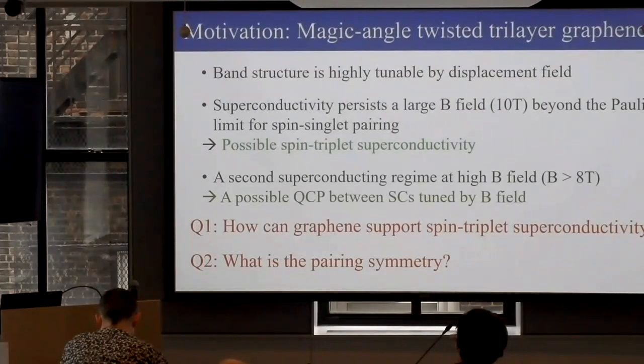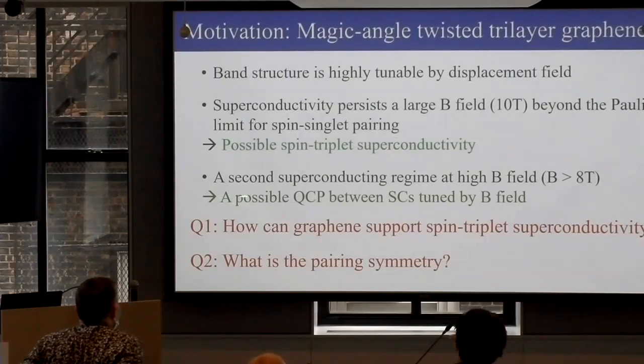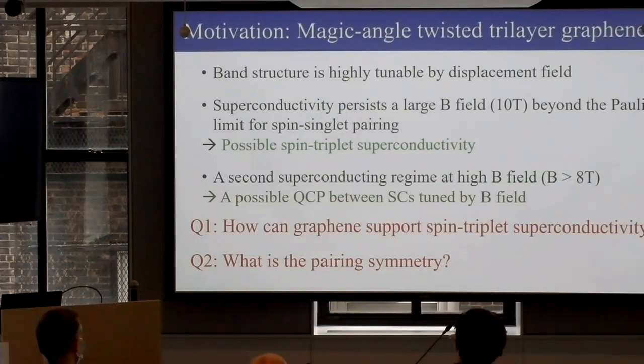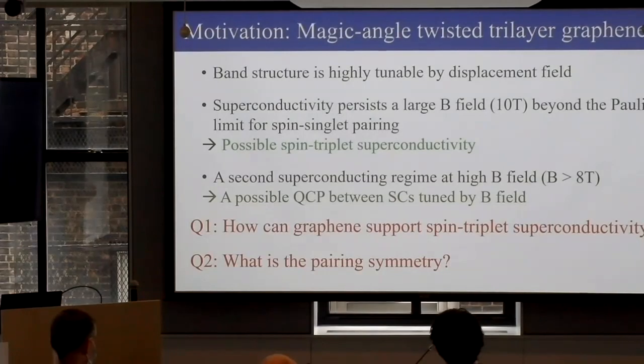Now the last topic which I want to talk about, because this is the electron, I said phonons are not. These two groups, Santa Barbara, Columbia, and MIT compete. So Pablo came up with a paper, it's all in Nature, where he saw superconductivity in twisted trilayer graphene, more or less at the same time these experiments were going. Here he finds the band structure is highly tunable by displacement field, and he claimed it's spin triplet superconductivity from electron-electron interaction. And why does he know that? He applies a field of 8 Tesla, and the superconductivity becomes stronger. So he calls me and says, can you explain this? First let me tell you, electron-phonon interaction cannot explain this. We did the calculation, it just doesn't agree at all.